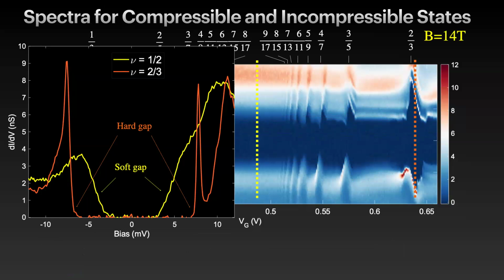Everybody has to get out of the way to add an electron. This scales with the magnetic length. You can check that. You go into the Laughlin state, this is the 2/3 state, and you add an electron. So normally you would think, I have a correlated state, and there's no overlap between an electron and whatever collective excitation or the quasi-particles of this collective state are. You do the experiment, and you see a very sharp peak.